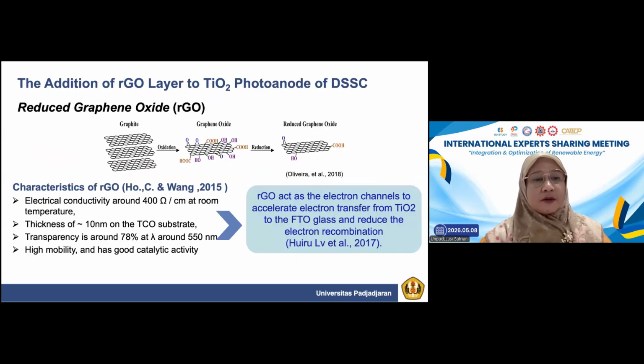So we modify the dye-sensitized solar cell. The TiO2 photoanode, with TiO2 as the semiconductor oxide, is the common material used for the photoanode of the dye-sensitized solar cell. We put a reduced graphene oxide layer into the TiO2 photoanode to increase the electrical property and also the optical property of the photoanode.